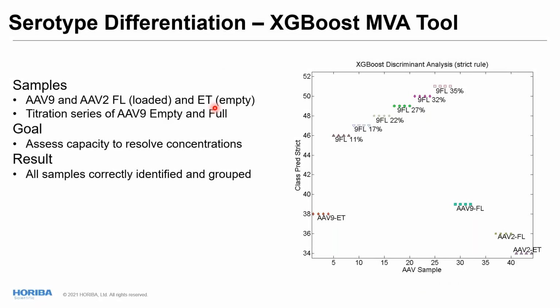We also wanted to look at the serotype differentiation. So the technique is very sensitive, and the surface proteins between AAV2 and AAV9 are different. So are we able to differentiate between these two? And what we see for this plot, and this is, sorry, an extreme gradient boost multivariate analysis tool. So this is a little bit of a different multivariate technique that we applied that uses some machine learning approaches. We see the empty versus full for the AAV9. And then we also see AAV2 empty and full.